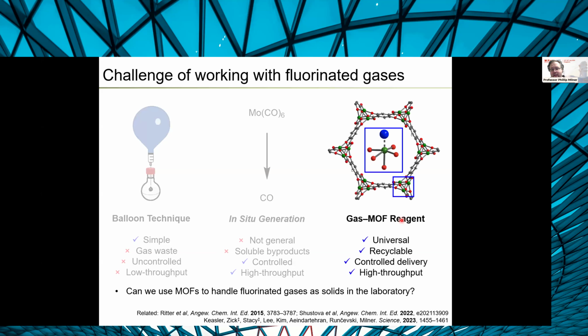Our idea was to take advantage of the porosity of MOFs and load up these kinds of fluorinated gases into these materials, which would allow us to handle them as solid reagents in the laboratory. This is nice because it should be universal. We can do this for any gas we want. These MOFs, of course, are heterogeneous. They're insoluble in organic solvents, so we can just filter them off when the reaction is done. We could actually weigh out the solid and add, say, 1, 2, 3, 4 equivalents of gas, however much we want. And I'll show you how that can be an advantage in just a bit. And it also enables us to set up tons of reactions and do high throughput reaction development with gases.